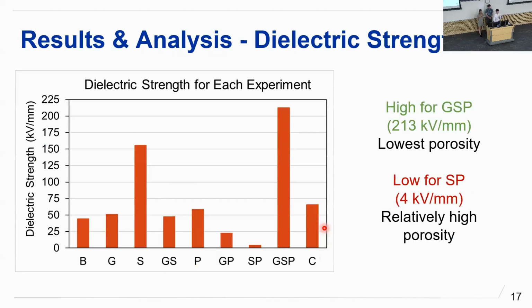So the analysis of our dielectric strength. Below we have a bar chart of all of our experiments, 1 through 9, where B is our baseline experiment and C is our center point experiment. And we can see that experiment 8, which had a high gas flow rate, a high stage speed, and a high number of passes, had the highest dielectric strength.